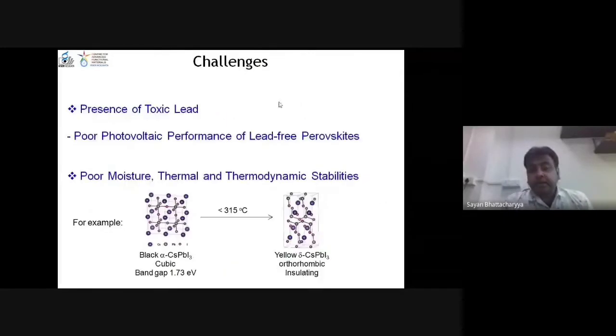But there are challenges, as I said, toxic lead. If you make lead free systems, the solar cell performance is not that good because of other reasons. And they are not stable in moisture, and thermal and thermodynamic stabilities are not good. So research is going on in this. I can tell you one example: CsPbI3 alpha phase, black in color. Below 315 degrees C, it transforms into the orthorhombic, yellow delta phase.